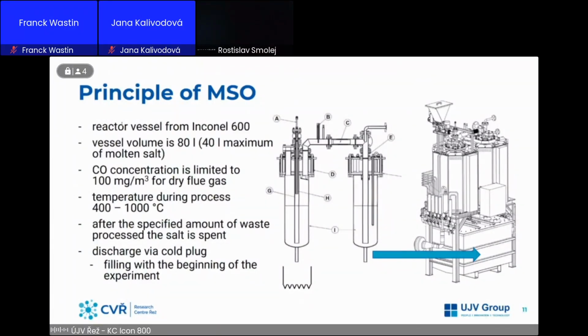And the good thing is that as you have two reactors, you can operate at two different temperatures. So, for example, in the first reactor, you can operate only at a temperature of 400 degrees Celsius, as you can use the eutectic mixture of alkaline carbonates, which is, for example, good for capturing cesium and other volatile radioactive materials. And the second reactor can be operated at much higher temperatures to process the secondary oxidation to be more efficient.